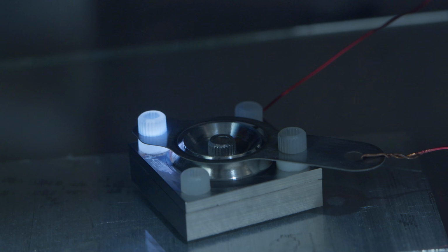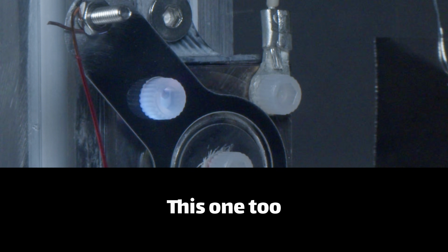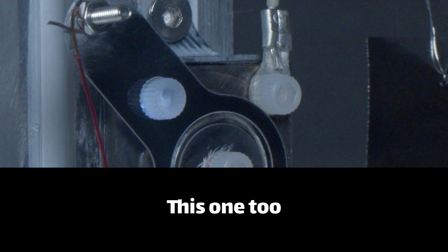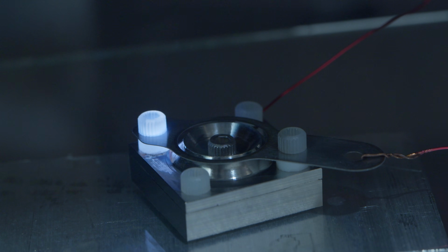This was both hilarious and terrifying at the same time. The screws are nylon, which is a good insulator, but it's also very hygroscopic. Under vacuum, nylon slowly outgasses water vapor. And I guess it had outgassed enough that the local area around the screw became sufficiently conductive that it could form a plasma. So yeah, that was exciting.